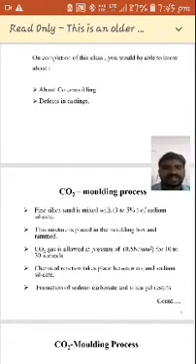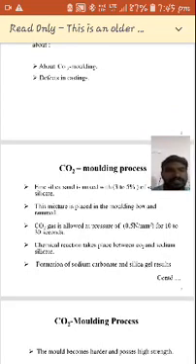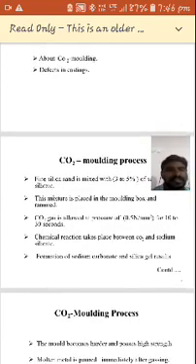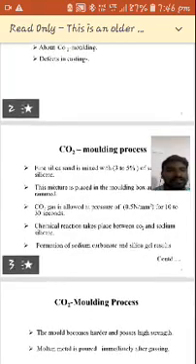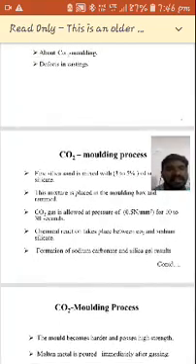See, if fine silica sand is mixed with 3 to 5% of sodium silicate. Okay, this mixture is placed in the molding box and rammed. So the aggregate mixture, that is silica sand and sodium silicate, will be mixed. Then the mixed sand is filled in a molding box, and after filling, we go for the ramming operation.